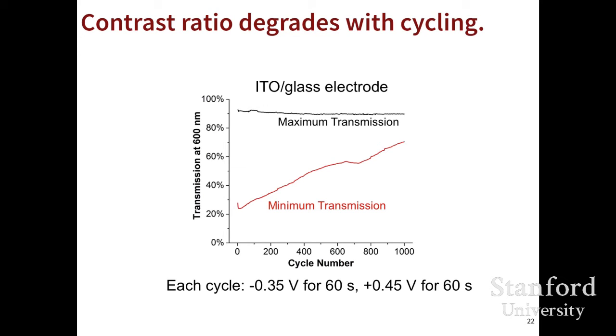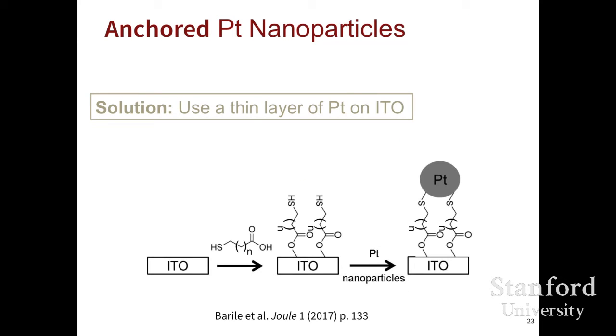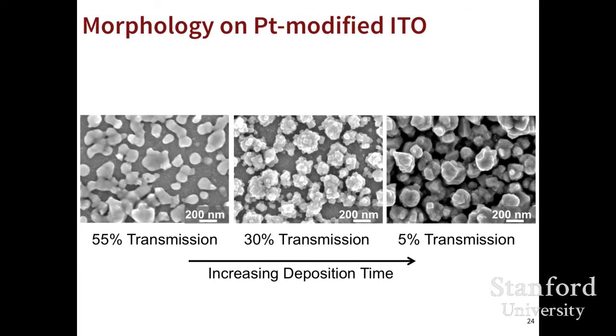Here you can see when we were doing a cycling experiment where we would plate for 60 seconds and then strip for 60 seconds, the minimum transmission was getting worse and worse over time. And then Chris decided that the problem was that only some sites on the ITO are good for plating metal. And so he attached platinum nanoparticles to the surface, knowing that metal will plate more easily on platinum than it will on ITO. And that worked really well.